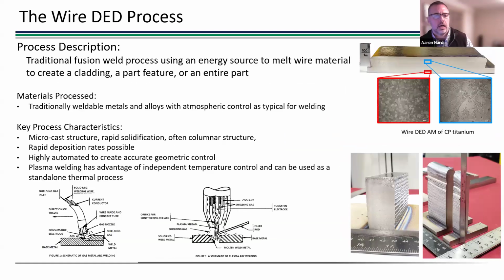The other technology I'll just mention is the wire DED process. In this process, you're taking what's a typical fusion weld process. I'm showing two examples. These are the technologies we use at VRC. One is gas metal arc welding, which is your MIG process, and the other is a plasma arc welding process. The main difference here is that in the gas metal arc process, you're using the wire short circuit against the substrate to create your arc. And then as that wire feeds, you continually create that arc, and you're melting the material.